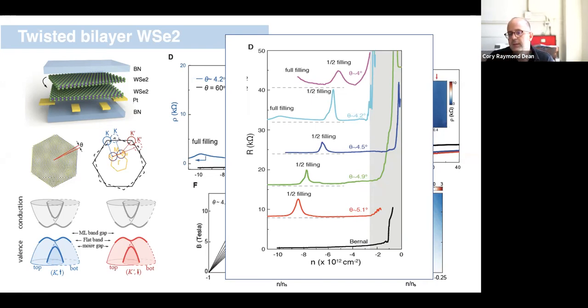Okay, so that tells us really 2 things. One is that the twist angle results in an evolution of the band width in the way that we expect. The other is that there is a finite range of angles, in this case, more than a degree of twist angle, over which we see the emergence of a feature at half filling of this band. And to be precise, I forgot to mention this, single particle band structure would not necessarily indicate that there should be any feature at half filling, really generally at all. And so we take this as evidence that we have basically a correlated driven insulating state that's emerging at half filling of this flat band system.